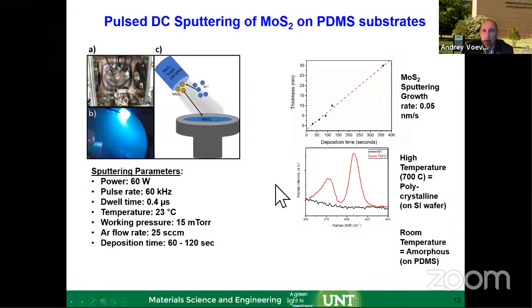So then the process became a two-step. In step one, you use a few seconds of growth, really we talk about 60 to 120 seconds of deposition time. We're using PVD sputtering of molybdenum disulfide, and you can cover as large an area as you wish. It's all amorphous. You can do it in plane here, moving the targets. You can do a roll of the polymer film, because you're producing at room temperature. There is no requirement for heating of the substrate. Everything becomes very simple and very quick. Again, we talk about 60 to 120 second deposition time.